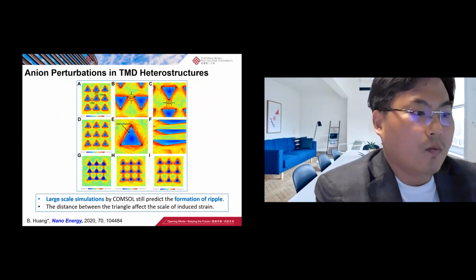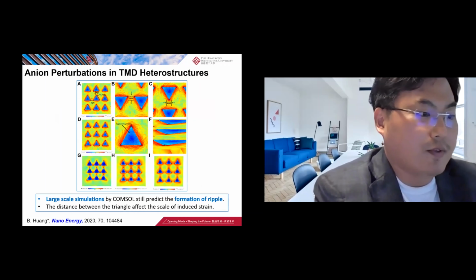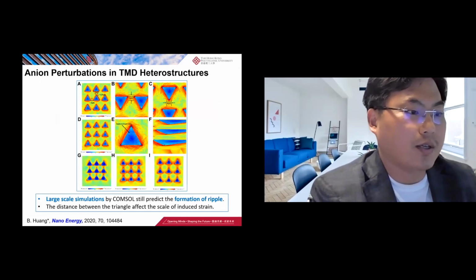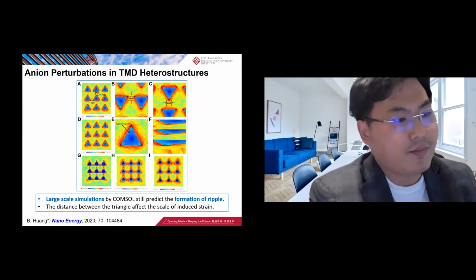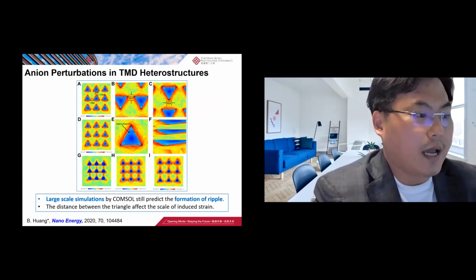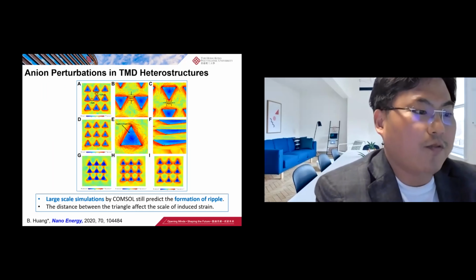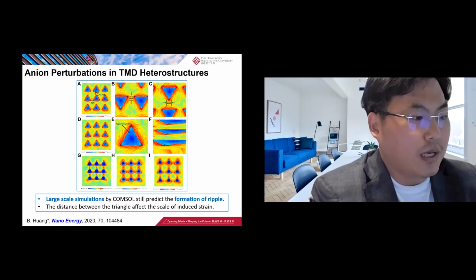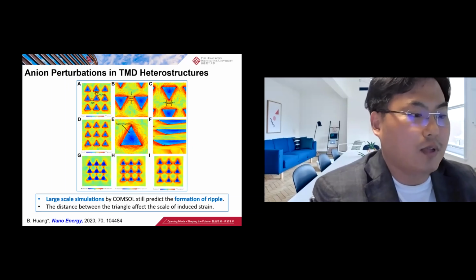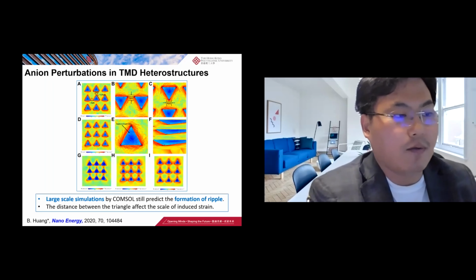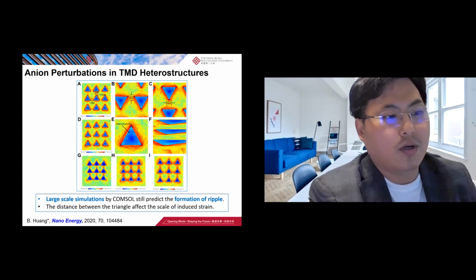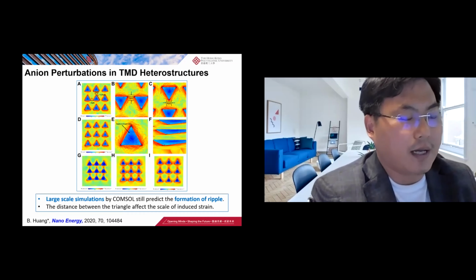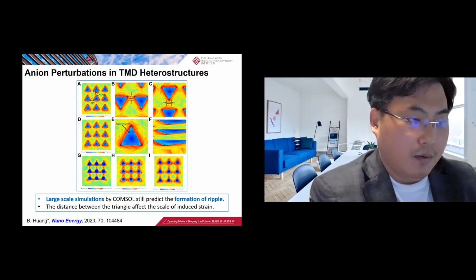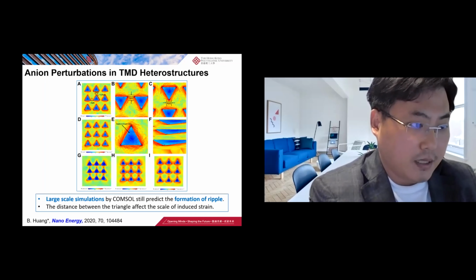In the end, we apply the so-called COMSOL software to reproduce the heterostructures with the same size as the experiment. At the edge end of the interface, we find the boundary effects are also interesting. We notice that ripple formation still exists, which means it is a large-scale extending general behavior, such as long-range orders beyond 10 angstroms or even approaching the micrometer scales. Meanwhile, the ripple scale will be affected by the interdistance of the arrays.